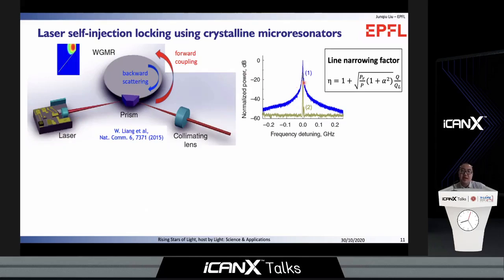significantly. The linewidth narrowing factor is proportional to Q over Q_L, where Q is the quality factor of the external microresonator, and Q_L is the quality factor of the laser cavity. I should mention that the linewidth narrowing is not due to external filtering, as the actual laser linewidth can be significantly narrower than the linewidth of the microresonator.